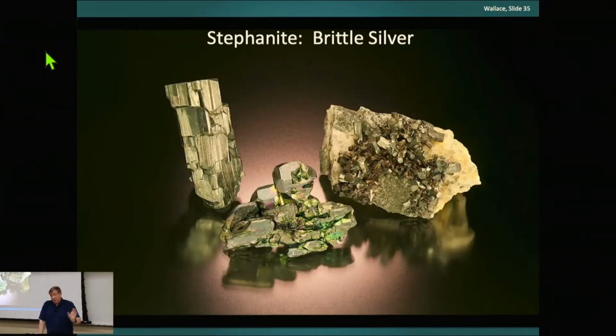Outside these, but still silver sulfides, is stephanite. It's called brittle silver. The one on the far left-hand side is actually almost a 3-inch crystal from Pribram. Below, probably recognized from the iridescence, is a Husky mine stephanite. And the last one over there on the right-hand side is a series of stephanites from Freiberg. The reason it's called brittle silver is that if you ever get a chance to have a really good stephanite and you decide you want to glue it to a little stick or something like that, you're screwed. Because it's likely that no matter what you do, unless you really soften that glue, you're going to break this material. It's very, very brittle.